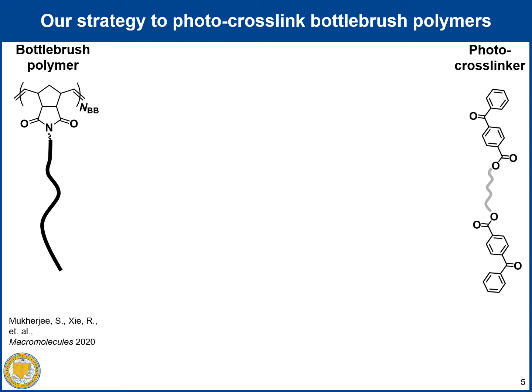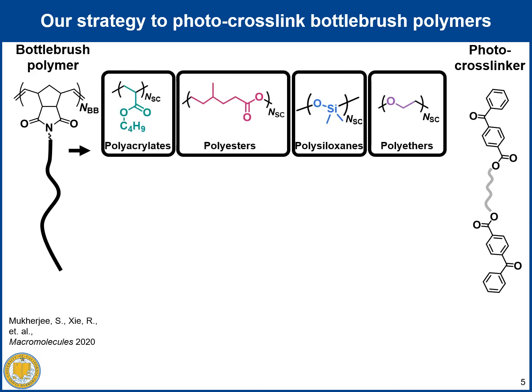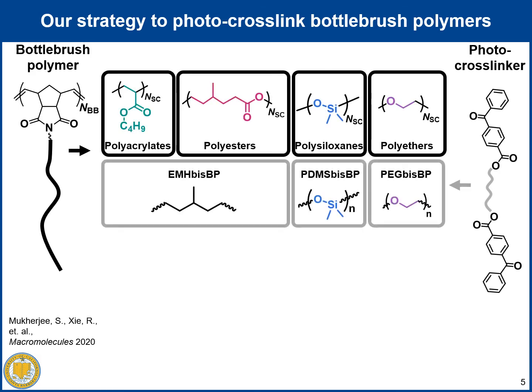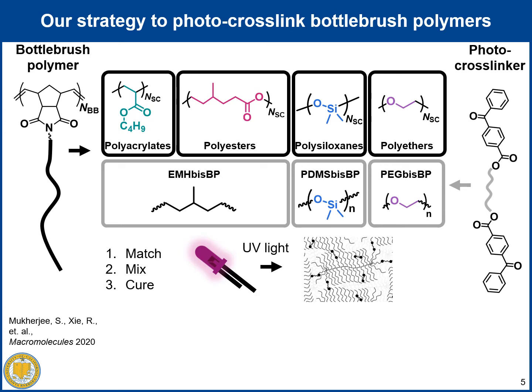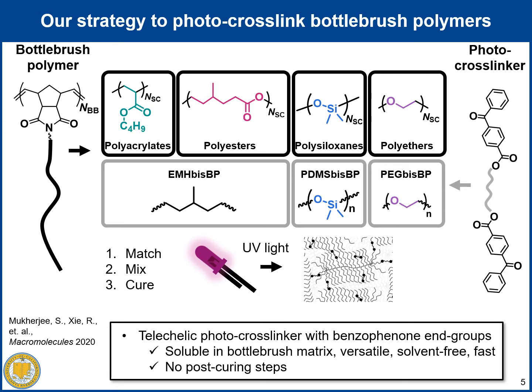Our approach starts with a mixture of bottlebrush polymer and photo-crosslinker, which will have different sidechain chemistry and different linker chemistry. And by matching their chemistry and similarity, we can assure good miscibility between the two components. And then by shining the UV light, the polymer can be directly cross-linked to form the bottlebrush network in a solvent-free state. Our design approach is potentially advantageous because of the solubility in a wide variety of bottlebrush matrix without solvent. We also expect a much faster cross-linking reaction from the bottlebrush polymer rather than from a mixture of macromonomer and crosslinker.